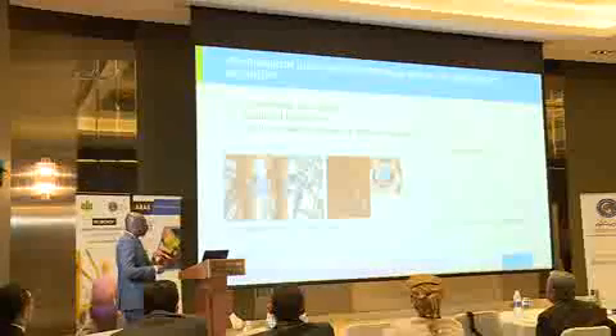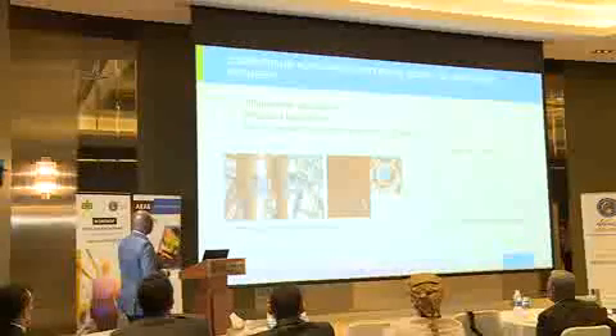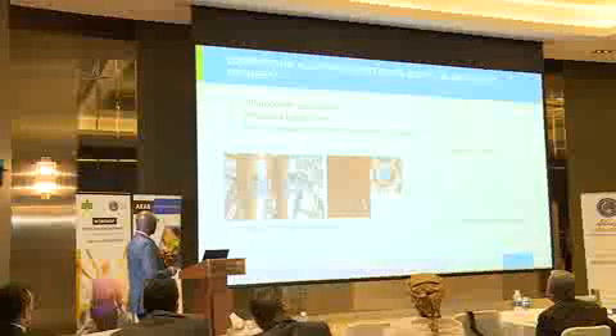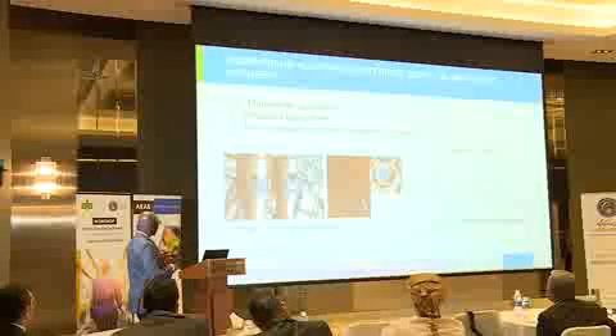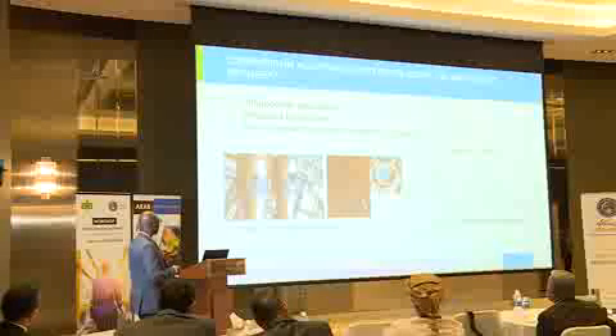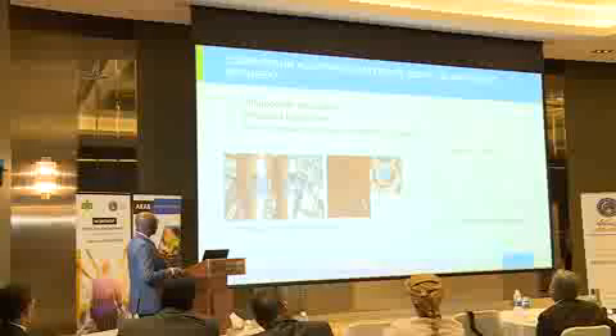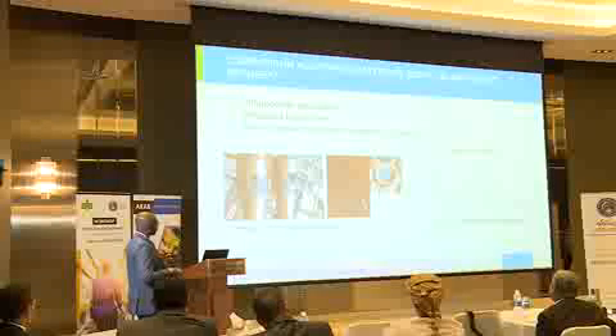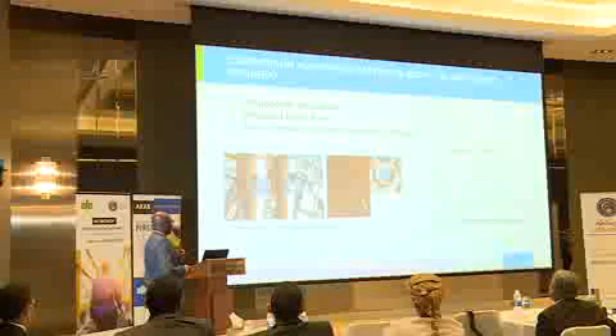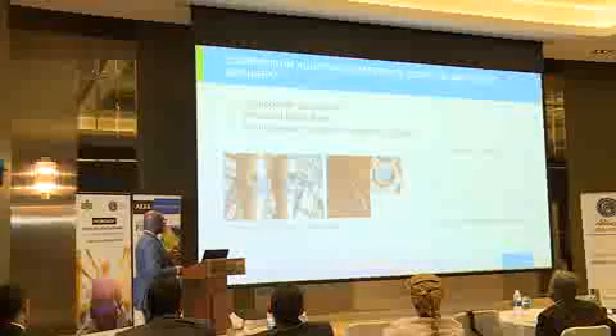How does Safurex fare under similar conditions? Now, this is a Safurex stripper. You have the same issue of fouling. And what this means, because you have this deposit of oil and corrosion product over here, you are not getting enough liquid into your tubes, so the tubes are running semi-dry. If you have an austenitic stainless steel material, this would rupture at some point. You cannot run to the next turnaround.